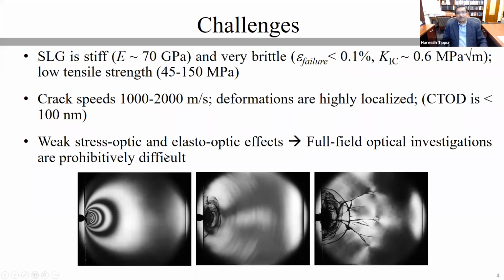Another challenge that we always come across with glass is that its elasto-optic properties are relatively weak. Stress optic constant and elasto-optic constant are both low, and I'm going to tell you what they are in a second. Full-field optical investigations with glass have therefore been prohibitively difficult. Here I'm showing at the bottom an experiment that we undertook a while ago where a projectile has impacted the edge of a plate. When the compression is dominant at the impact point, the photoelastic fringes form very nicely. On the other hand, when cracks begin to propagate, fringes disappear very quickly, and a propagating tensile crack usually does not have any fringes at all for us to analyze.